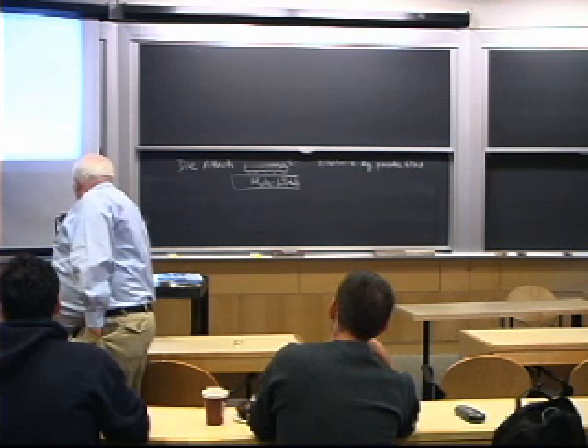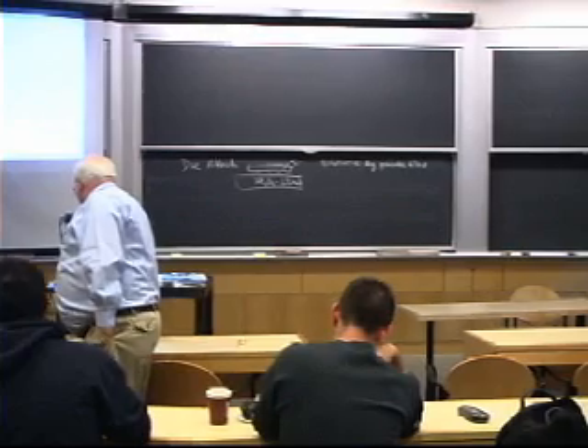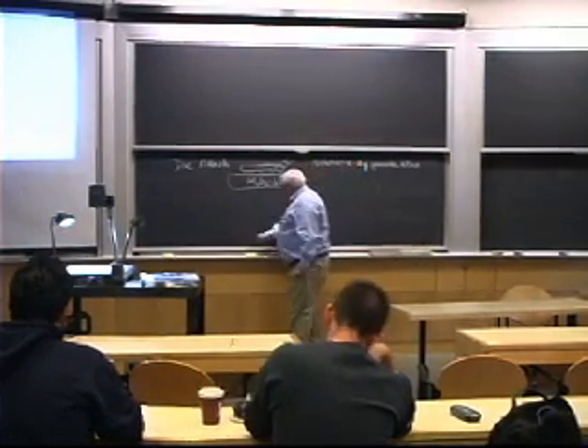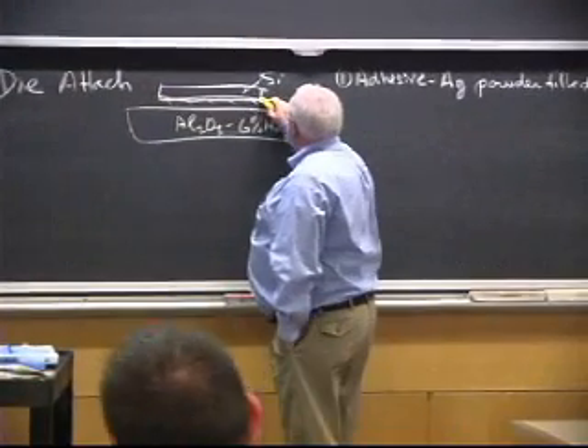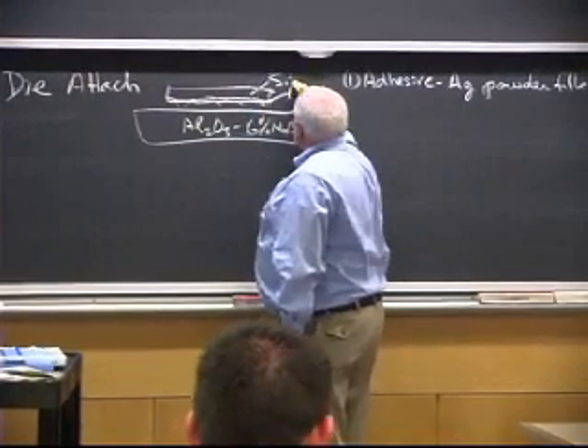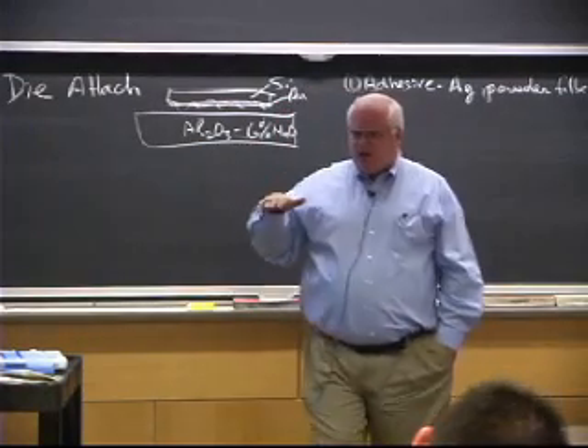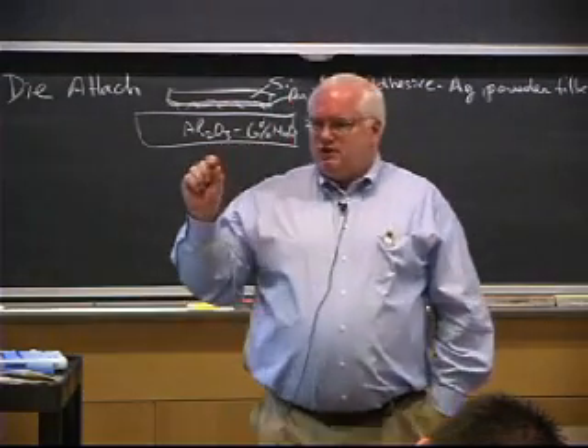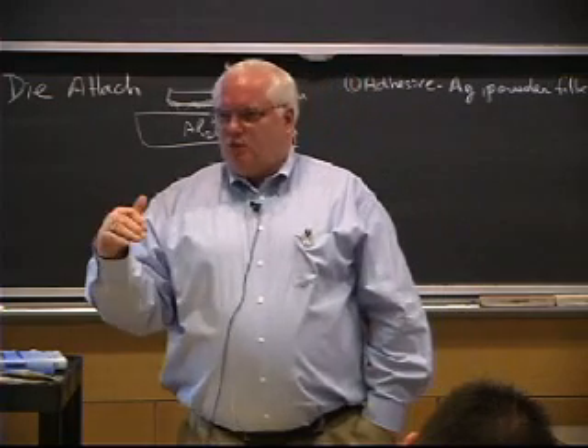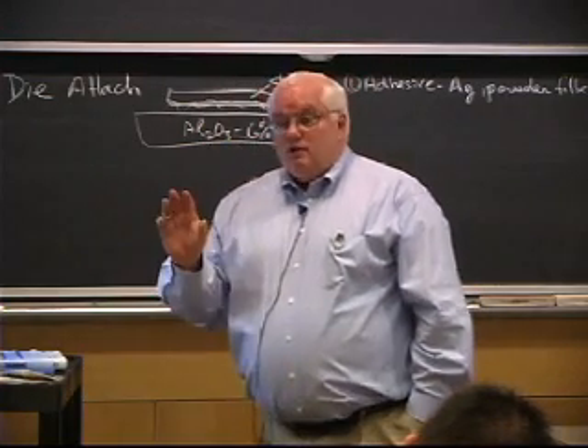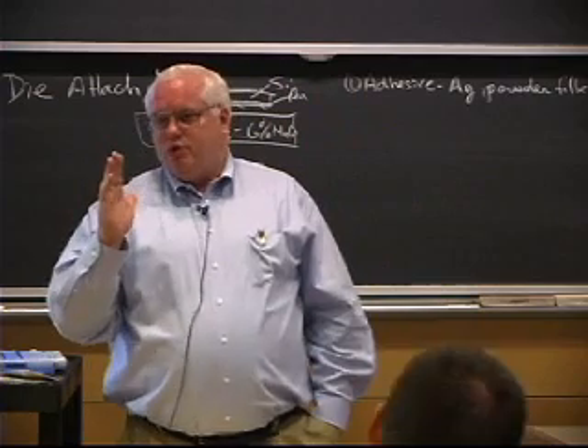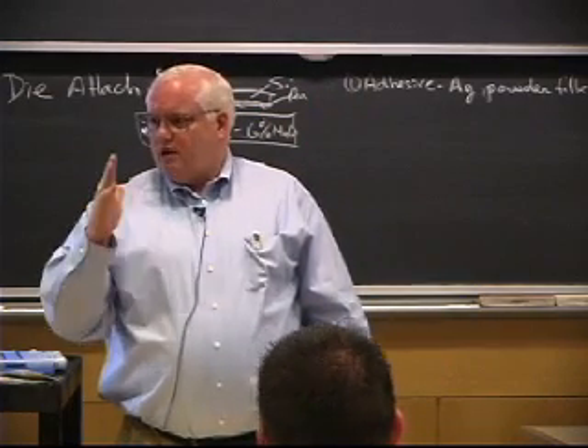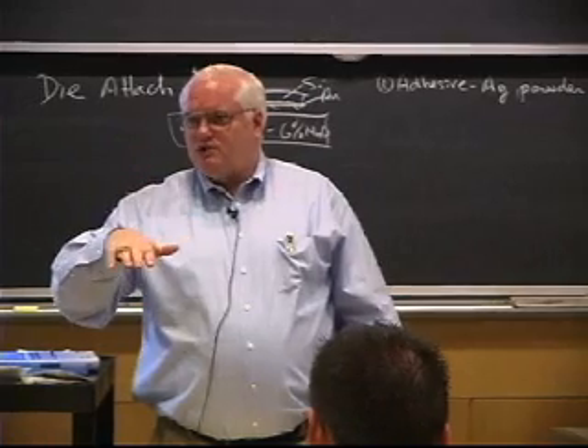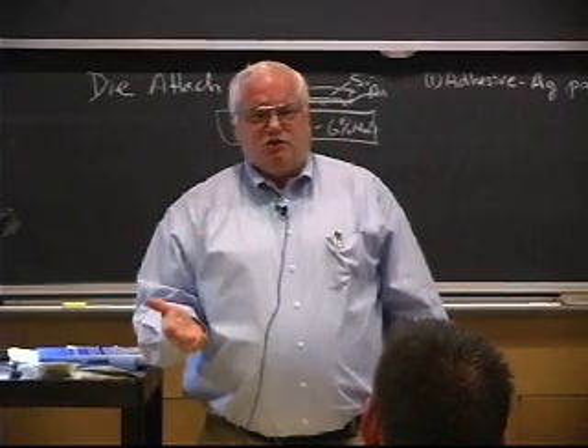Now, virtually all of these chips nowadays at these high frequencies, when you're getting into the 500 megahertz and above, the silicon actually has a layer of gold on the backside. They metallized it, they vapor deposited a thin layer of gold as the ground plane on the backside. I'll try to remember to bring one tomorrow. But the Pentiums I passed around actually had gold on the backside. You can see the chip on one side with the circuits. You flip it over, it's just a gold coating.